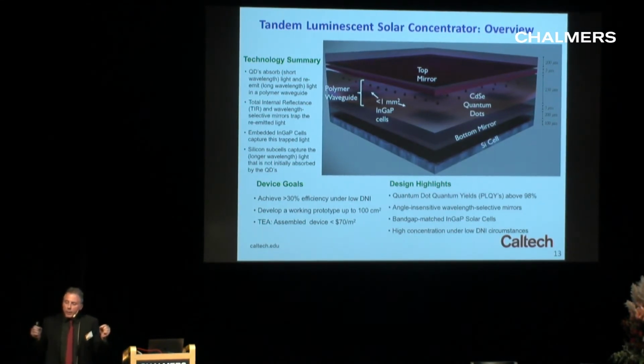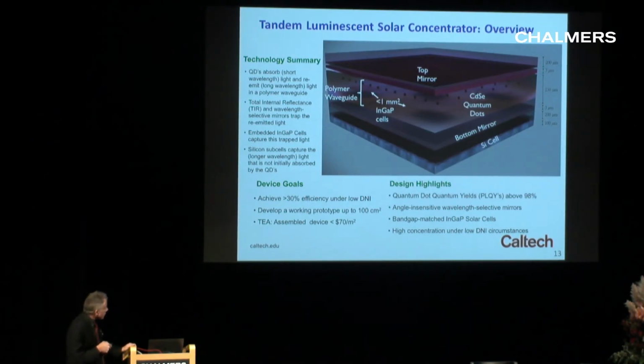That means we need to be able to make only 1% of the flat area be the solar cells. To do that, we need a concentrator of a factor of 100. And as Paul told you yesterday, we have a luminescent solar concentrator that can produce a factor of 100. So this is a tandem combination that produces here not gallium arsenide, but indium gallium phosphide cells, a similar sort of process that I described before, to enable modules with greater than 30% efficiency.